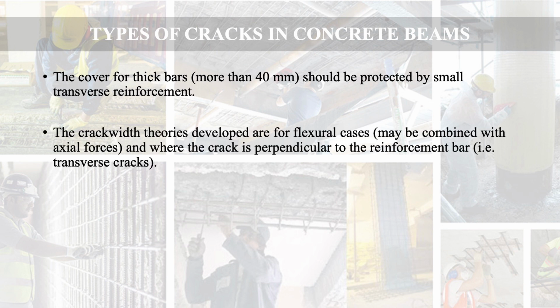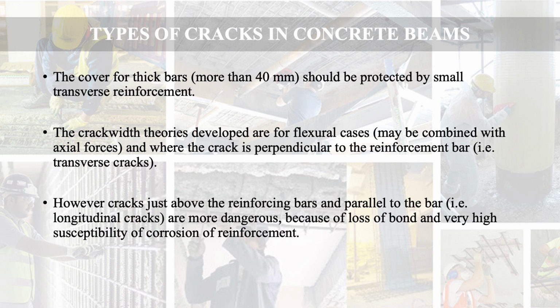The crack width theories developed are for flexural cases, may be combined with axial forces, and where the crack is perpendicular to the reinforcing bar, that is transverse cracks. However, cracks just above the reinforcing bars and parallel to the bar, that is longitudinal cracks, are more dangerous because of loss of bond and very high susceptibility of corrosion of reinforcement.